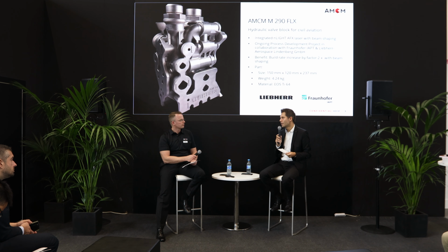Yep. And therefore I also see the increase of the process regime, because sometimes the process is not running, even if the machine says it's 100% all the same values. There are slightly different differences within a machine, of course. And therefore, sometimes using a Gaussian beam profile leads to the effect that you are running out of these boundaries, and therefore sometimes you get some pores where you normally do not have pores. And the process regime by using these ring shape profiles is much wider, and therefore you're not running so fast out of these boundaries, and therefore this is also a very, very nice indicator for process stability, which goes along.